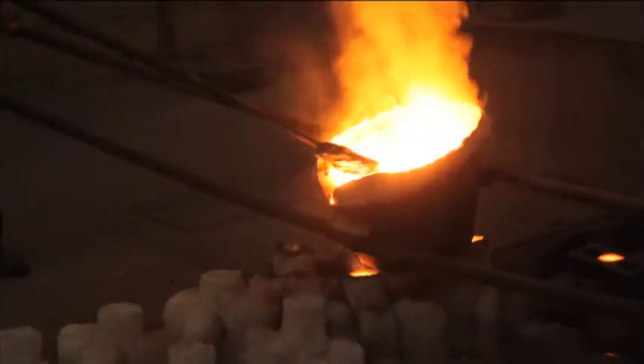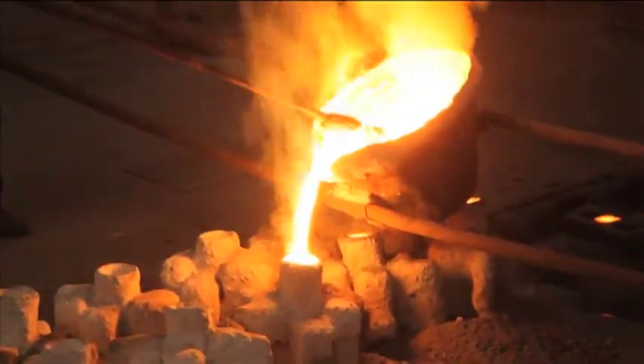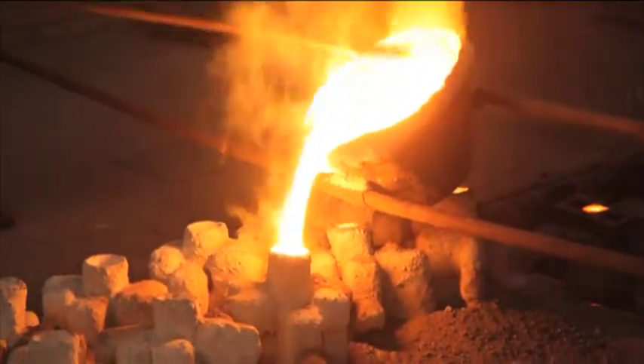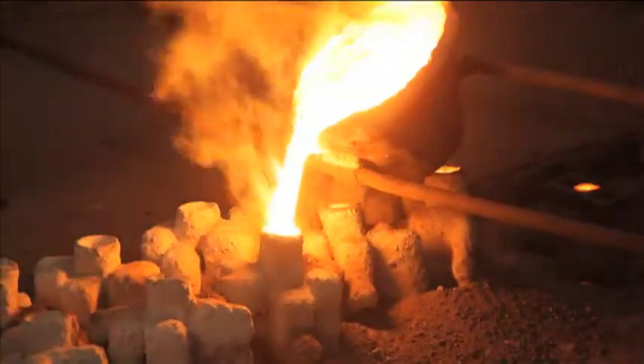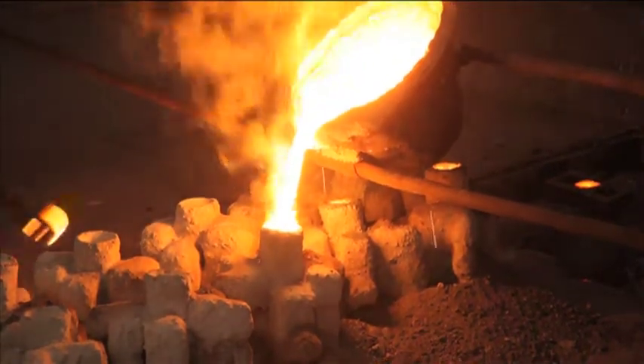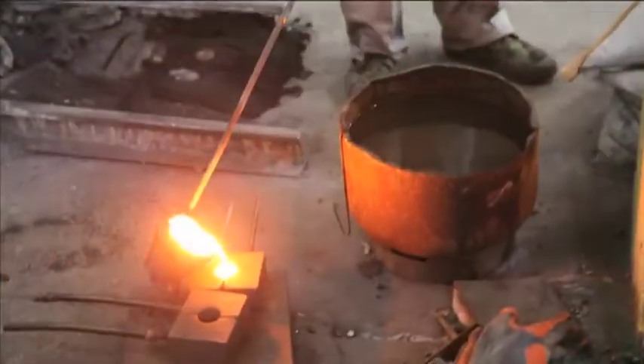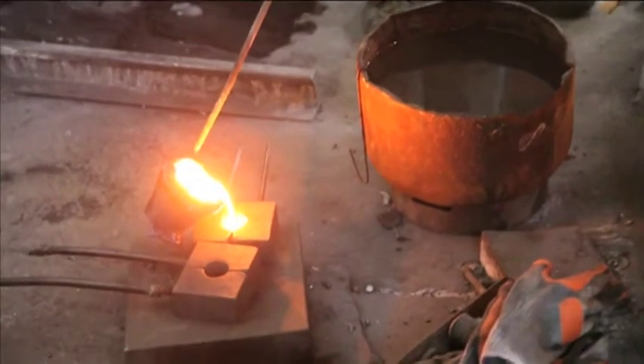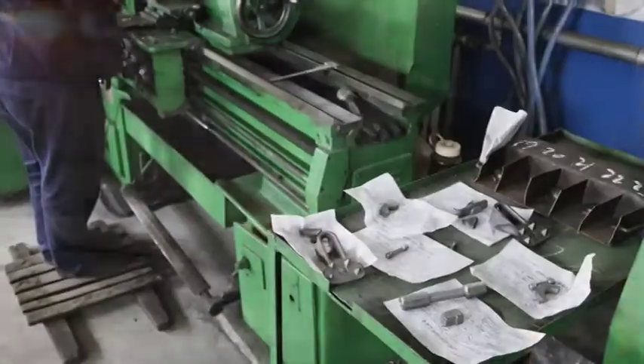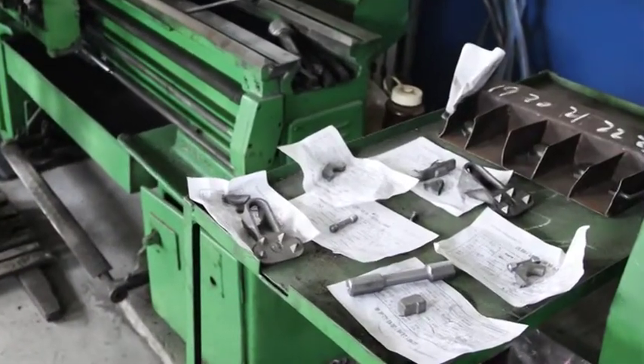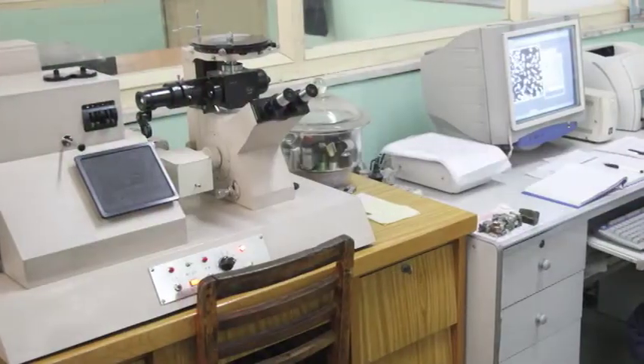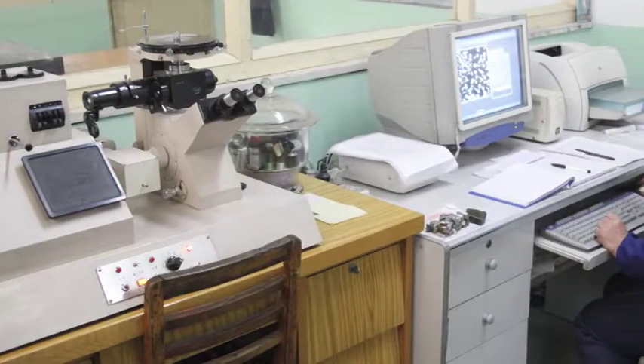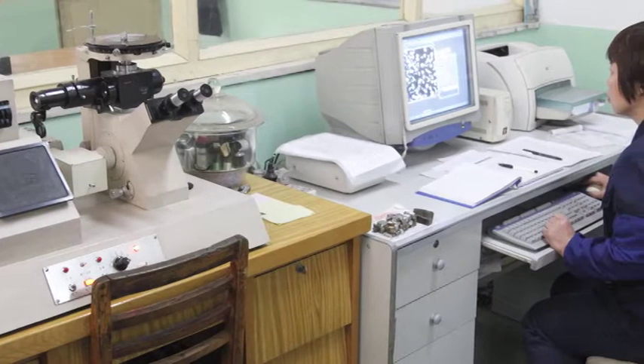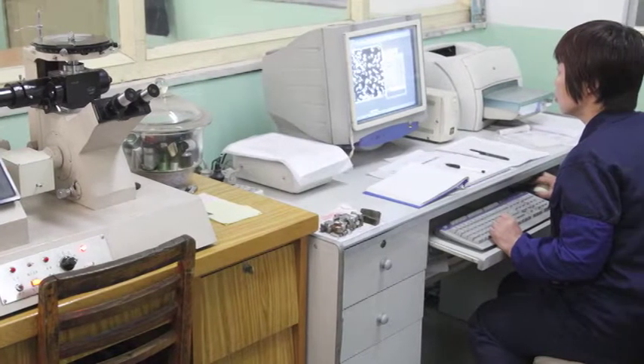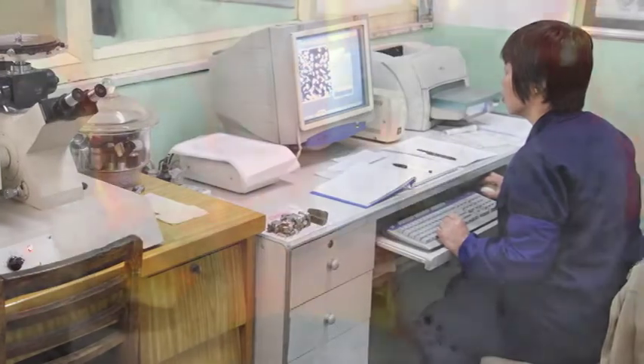Up to 3 tests with a spectrometer are sometimes required to ensure the melt meets specifications for the required steel. Once the melt is approved, it is released for pouring into the mold clusters. During the pouring process, 2 keel or test blocks are also poured for each batch of mold clusters. These keel blocks are then cut into 3 test specimens. Only when these samples have passed the required chemical analysis will the batch of poured rough twist lock castings be approved for breakage from the cluster and heat treatment.